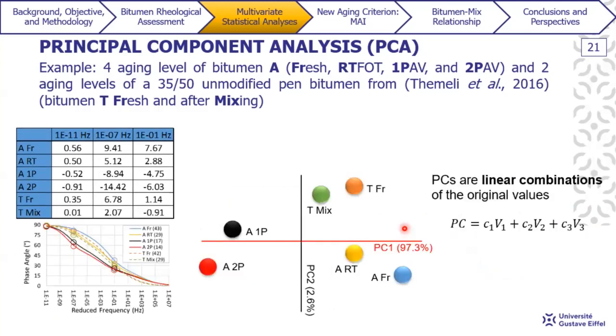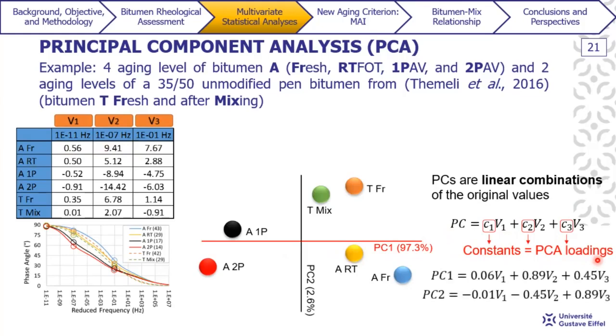Now I'm just gonna make some room here. Yeah, so the axes of the PCA scatter plot are a linear combination of the original variables. In this case, these constant values that multiply these mean centered values are called loadings in PCA, and the higher the loading value, the greater the relevancy of the original variable to the PC. In this case, for PC1 the highest value is V2. V2 corresponds to this column here in the middle, whereas for PC2 it is V3, that is the rightmost column here.